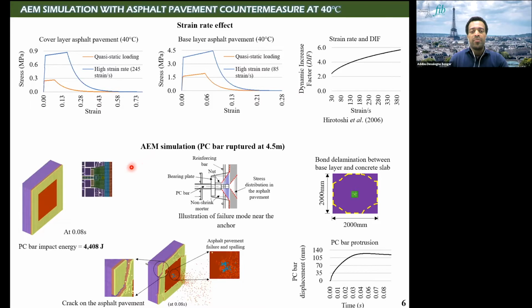So this one is the AEM simulation when the bar is ruptured at 4.5 meters. It means the impact energy is around 4,400 Joule. This one is the 3D view, and this one is the section view near the anchor. And this one is the illustration of the failure mode near the anchor. This time, two diagonal stresses originated from the head of the nut and from the head of the PC bar, and create a conical crack in the mortar and in the asphalt pavement.